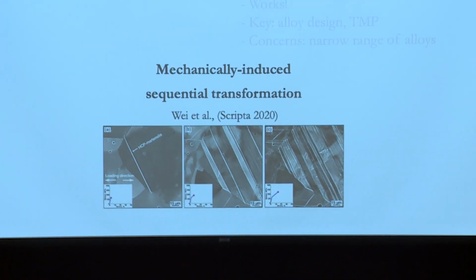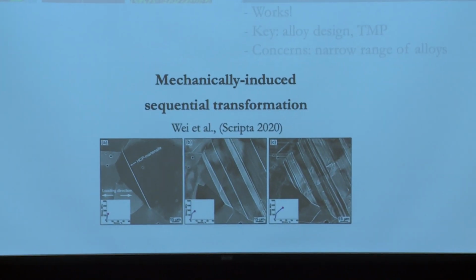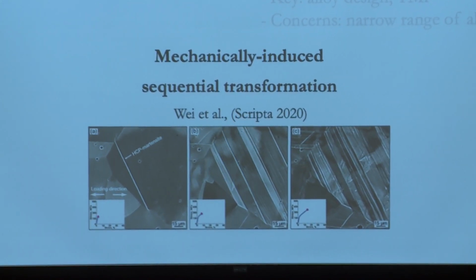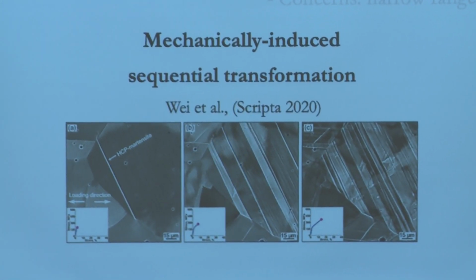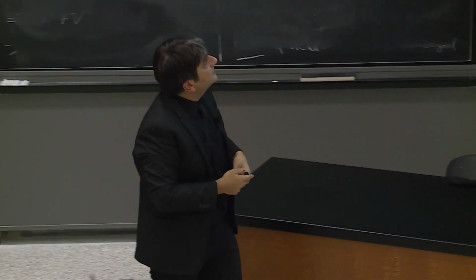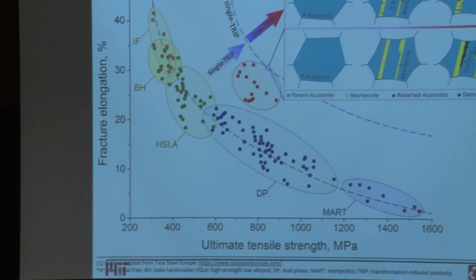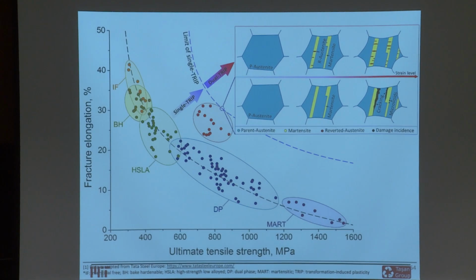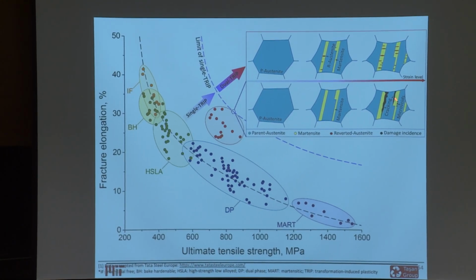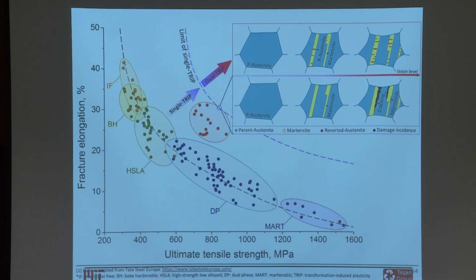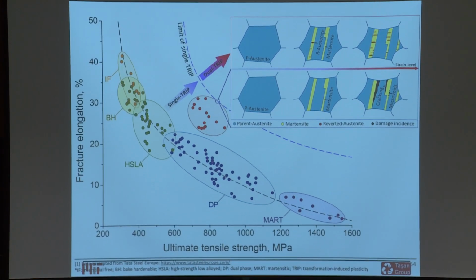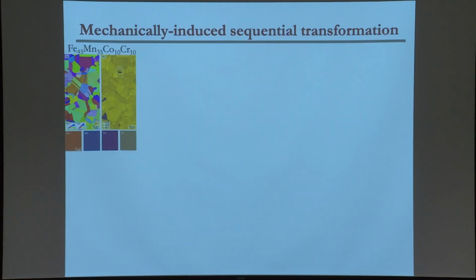The third idea is mechanically induced sequential transformation. And here, let's go back to our problem again. Our problem was we want the forward transformation. We don't necessarily want the end product. So maybe you can design systems where you have the forward transformation, and then you have another transformation taking place. So you create a sequential transformation mode. And this is Shaldo's work that showed that this is essentially something like a dual TRIP effect, right? Double transformation induced plasticity effect. So instead of having the cracks here, we would have a second phase that is introduced, and this would perhaps bring additional strain hardening and so forth.